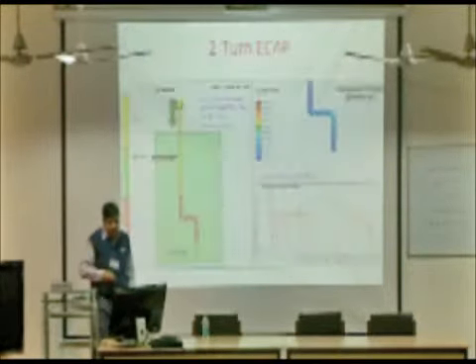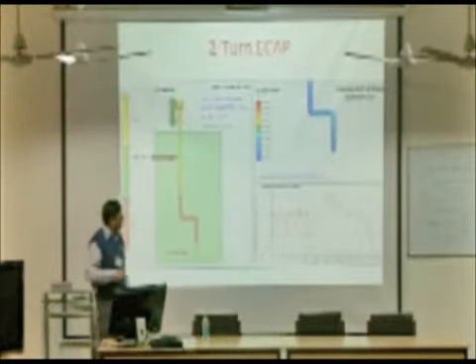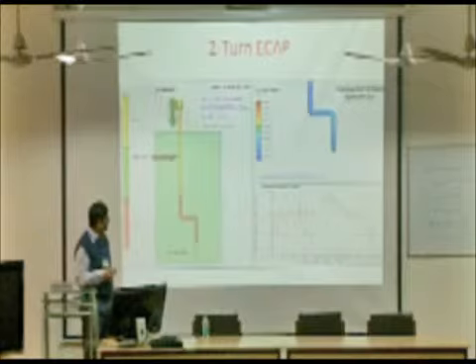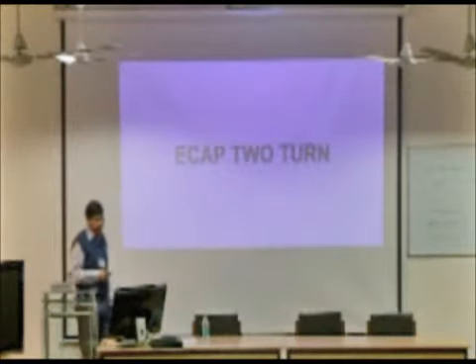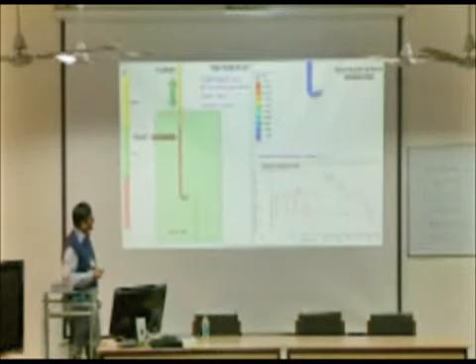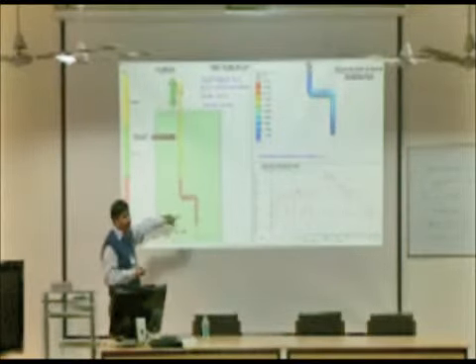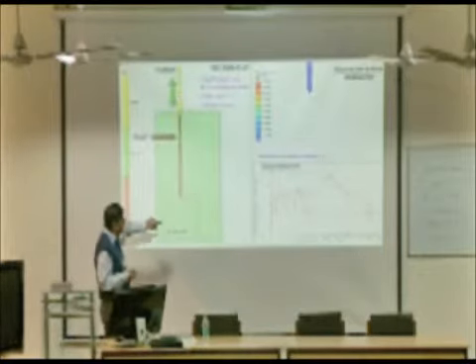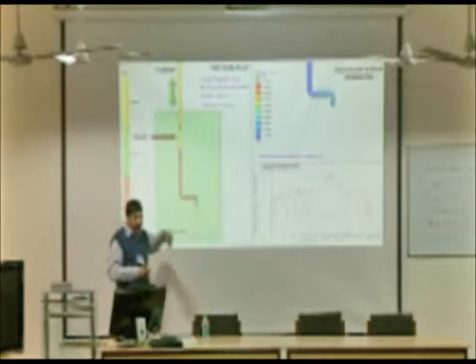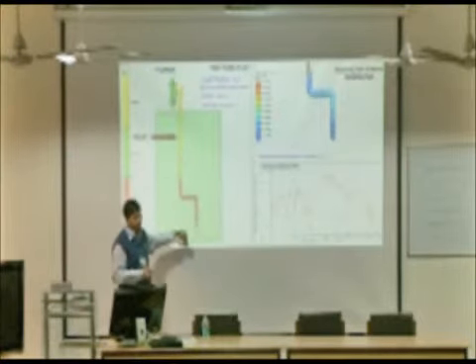These are some proposed designs that we have discussed. I'll show it here, the 2-turn ECAP that we have tried, and this has not been reported. This is the FEM simulation for the 2-turn ECAP. This is a concept, because in normal ECAP only one pass is given. In this, in one go we are getting 2 passes. But the problem is that the billet gets stuck. To get it out, we have to put in one more billet, then the first one will come out.